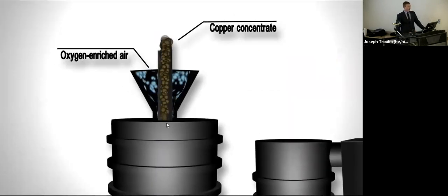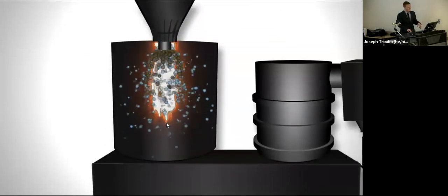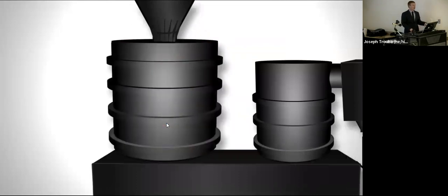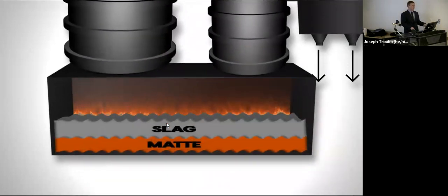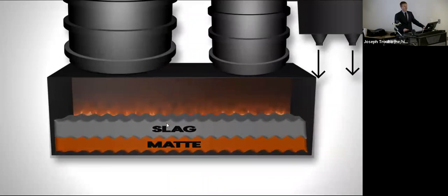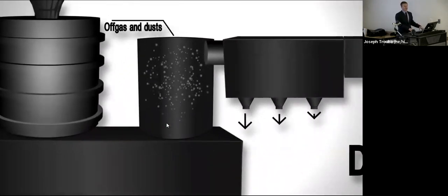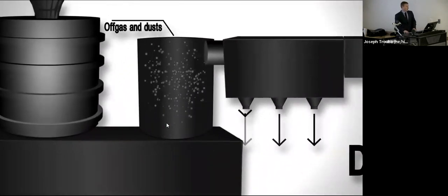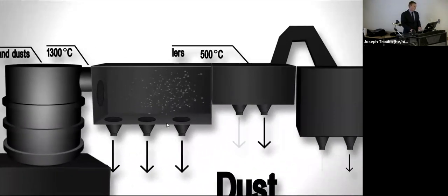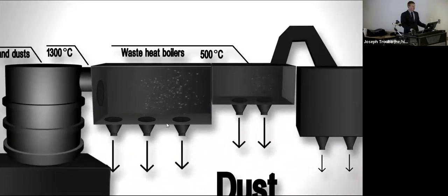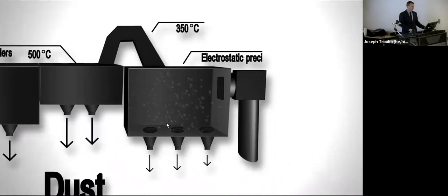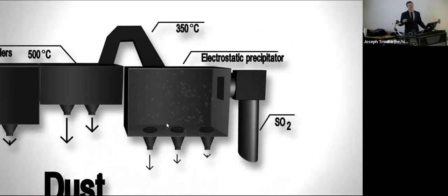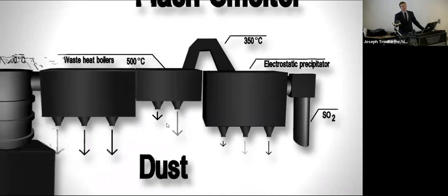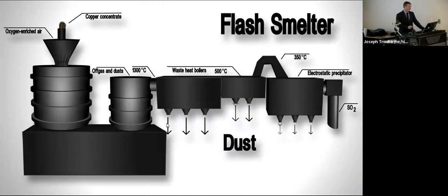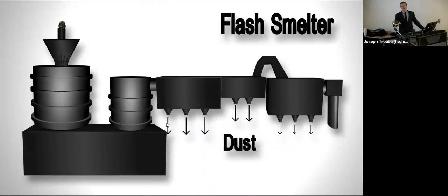Now we have to figure out how we're going to recover indium from the flue dusts. So the way dusts are generated, oxygen enriched air and the ore comes into the smelter. And it's a heavily oxidizing environment with high gas flows, which leads to considerable formation of dust. 5 to 10% of the mass of concentrate ends up in the dust. First, there's a waste heat boiler, which cools the off gas and dust from 1300 to 500 degrees C, where it then enters an electrostatic precipitator, which cleans the gas a little bit more. The SO2 is then recovered in an acid plant.